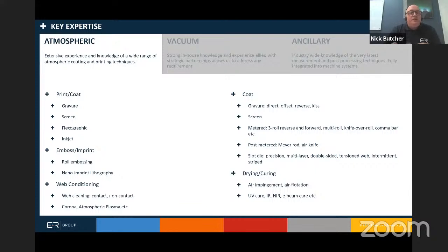We've then taken it one step further, and we've taken traditional mechanical embossing, which we have at very, very high accuracy, and we're supporting that with more advanced nano imprint lithography. In these areas, we're pushing the envelope to take roll-to-roll solutions that today exist in the semiconductor world down to 50 nanometers and less. We're also developing machinery now in roll-to-roll that will allow us to coat down to 0.5 micron wet, with a dry coating leaving us at 50 nanometers in some of our structures.